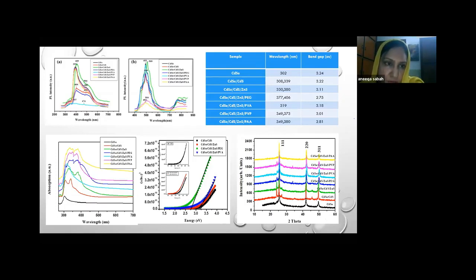We have the PL (photoluminescence) spectra. We also find good absorption peaks within the range of 300 to 320 nanometers wavelength, and transparency beyond this. Band gap was simply measured, and the cubic phase of these quantum dots was observed.